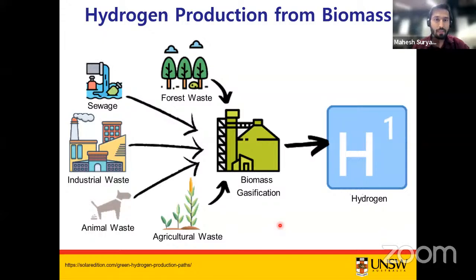Gasification is a process that converts organic or fossil-based carbon-based materials at a very high temperature, around 700 degrees centigrade, without combustion or with a controlled amount of oxygen and/or steam, into carbon monoxide, hydrogen, and carbon dioxide. This carbon monoxide then reacts with water to form carbon dioxide and more hydrogen via the water gas shift reaction. Again, the absorbers or special membranes used during biomass gasification can separate the hydrogen from this gas stream, and finally we can collect pure hydrogen and further store it for later use.